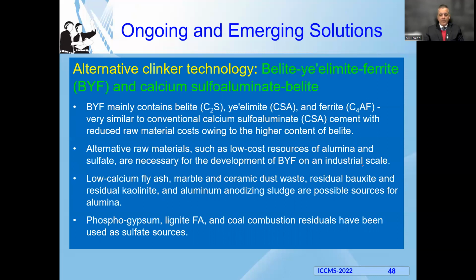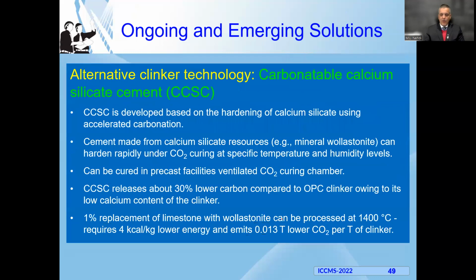Similar or somewhat related, along the same lines, is the belite, yeelimite, ferrite, and calcium sulfoaluminate belite. And here essentially, products similar to calcium sulfoaluminates. But to be able to produce these, we need cost-effective sources for the raw materials to be able to produce these more sustainable cement alternatives. So maybe as sources of alumina, we could resort to things like low calcium fly ash, marble and ceramic dust waste, residual bauxite, residual kaolinite clays, and so on and so forth. And as far as the sulfate sources go, maybe phosphogypsum, coal combustion residues. So this will depend on the local context and whether we have access to sustainable sources of raw materials to produce these kinds of alternative clinker technologies.